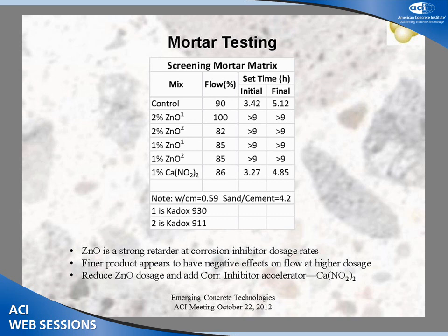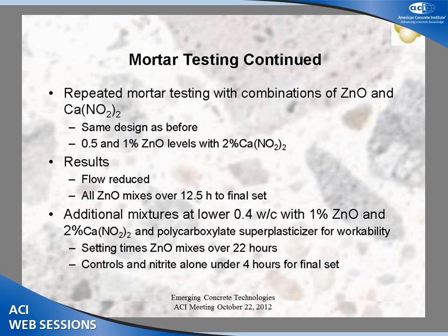But you can see with the inclusion of the zinc oxide at 1 and 2%, the set time tests were halted basically at the end of the day. So all we know is that the time to initial set and the time to final set with the zinc oxide was in excess of 9 hours.